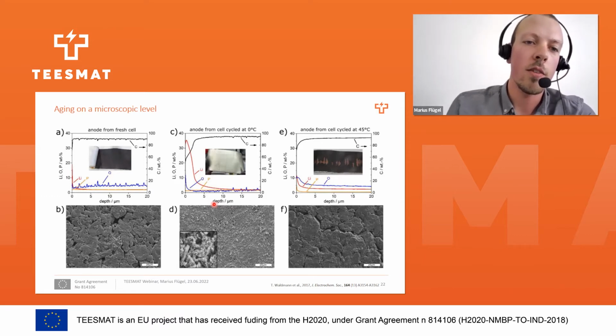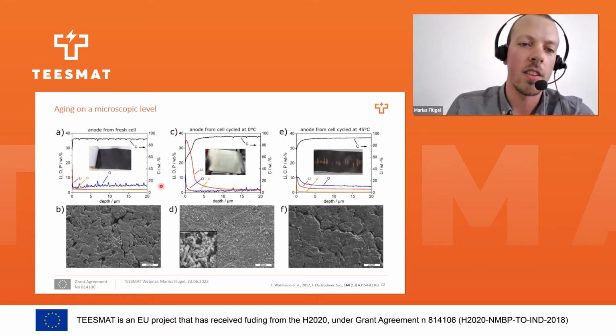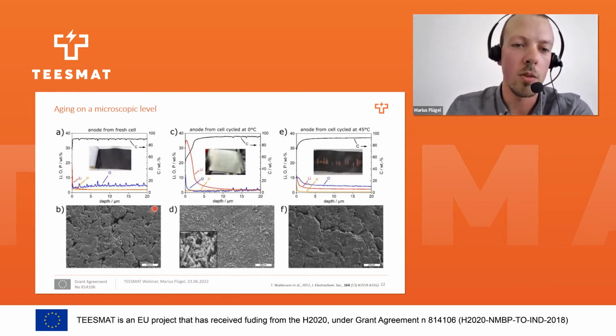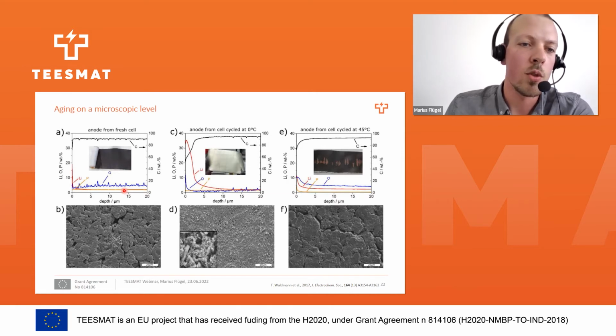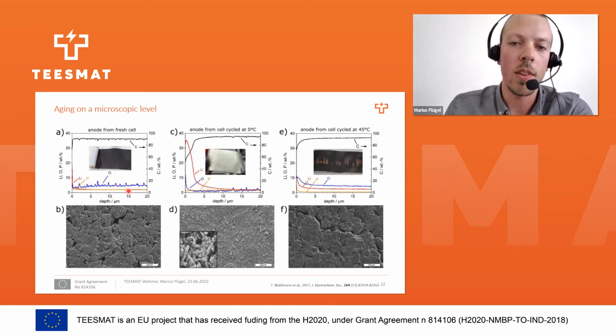On the left, you can see a fresh cell. With SEM, you can see the pristine surface, and one can distinguish the individual particles. With the GD-OES depth profiling, we see a normal depth profile. We see lithium to a normal degree and also phosphorus.